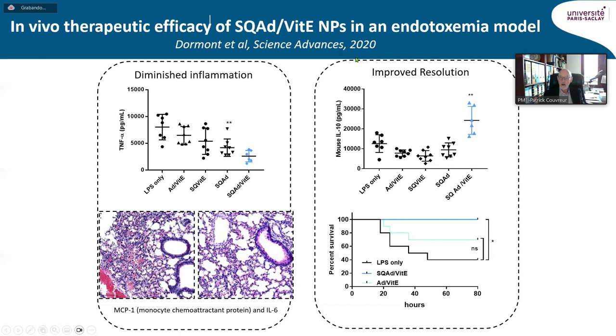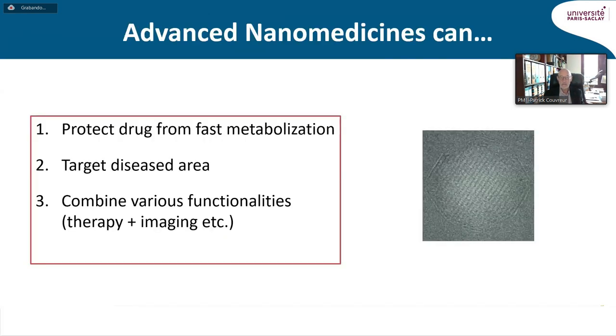On the other side, we observed that the resolution of the inflammation was also improved, as you can see here in blue, through an increase of IL-10, which is an anti-inflammatory cytokine. And the result of that was that those multi-drug nanoparticles in this endotoxemia model allowed us to obtain 100% survival, whereas there was only 60% after treatment with the adenosine and vitamin E free drug cocktail, and only 40% for the untreated animals.